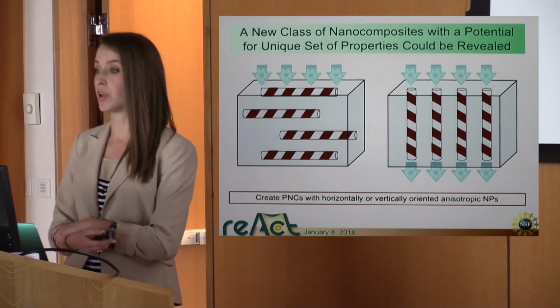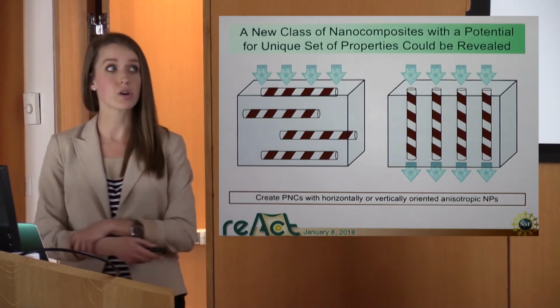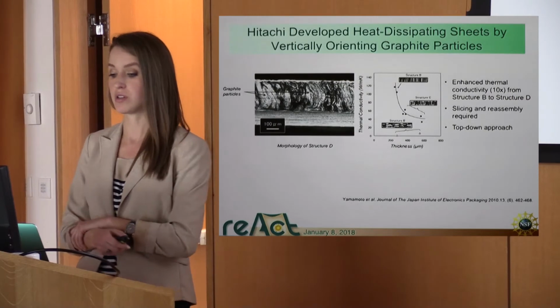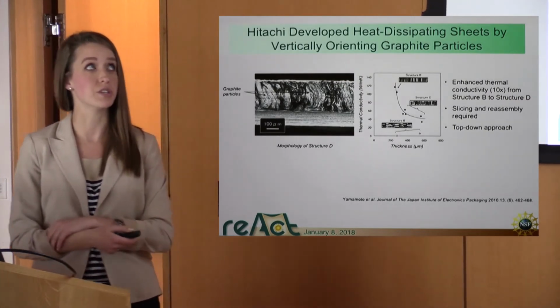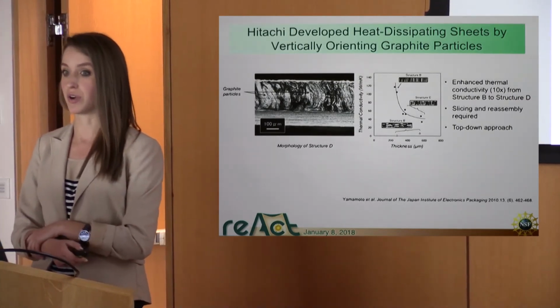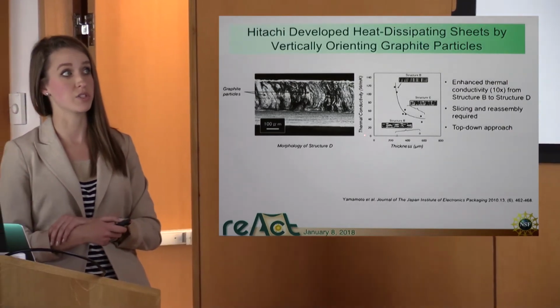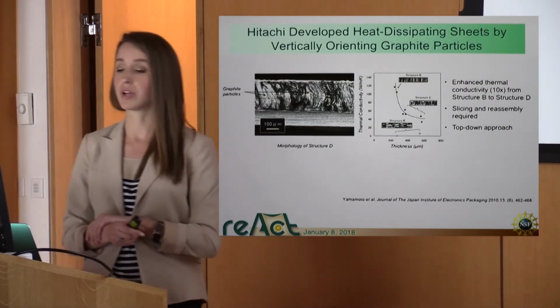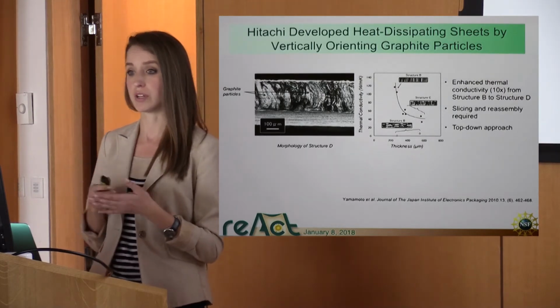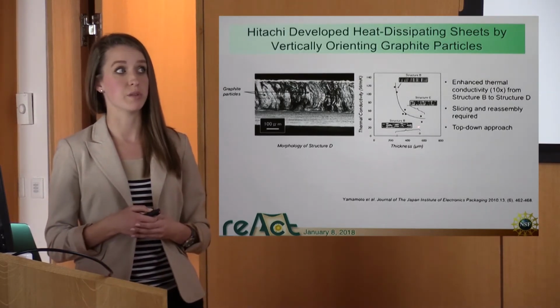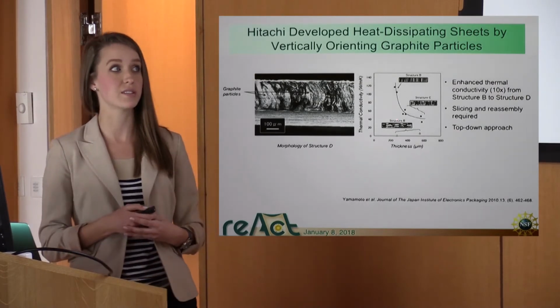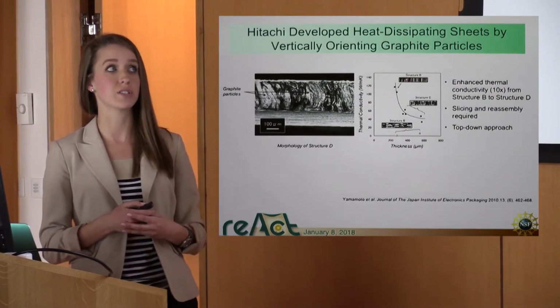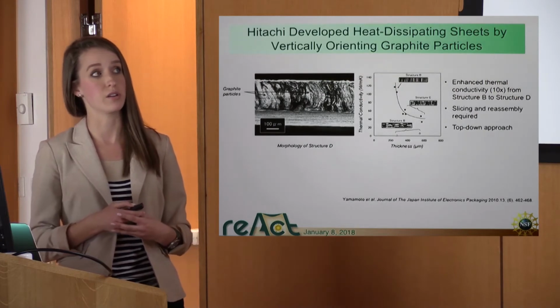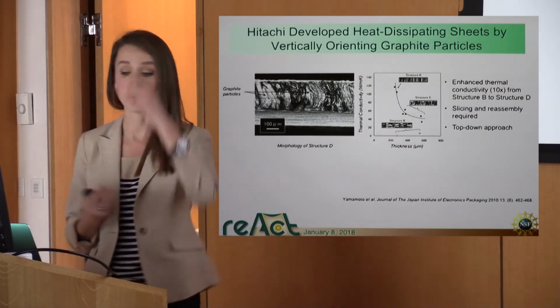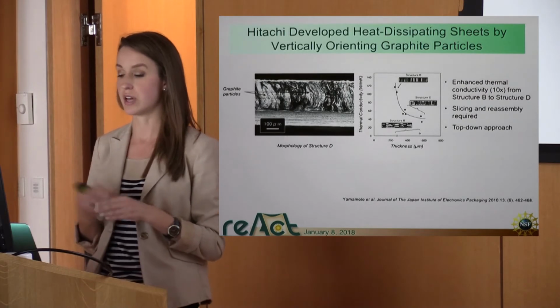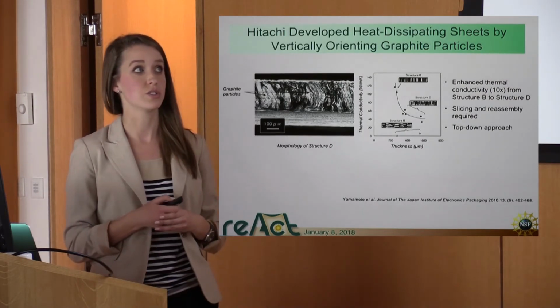So there's different ways in which we could think about doing this. We could apply external fields, or in the case of Hitachi Chemical Company, they developed heat dissipating sheets by vertically orienting graphite particles. And the way they did that was they took this structure B, where they incorporated graphite sheets into a thermoset resin, and it started off with the particles being parallel to the substrate, and then they sliced up this structure and reassembled it to obtain structure D, which we see here in the image. And what they exhibited was an enhancement of thermal conductivity tenfold, going from structure B to structure D.